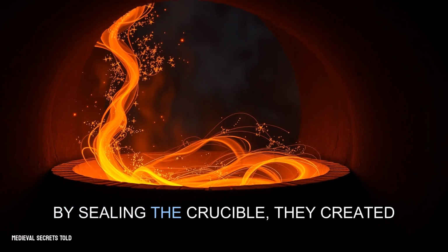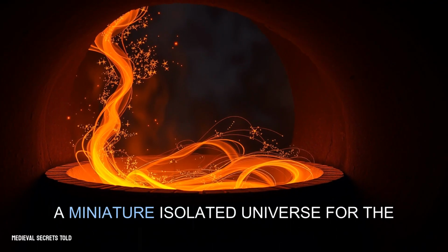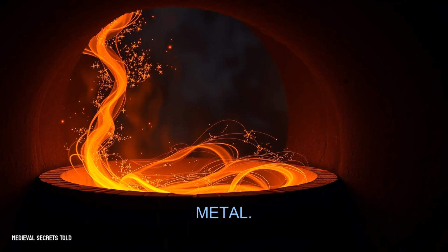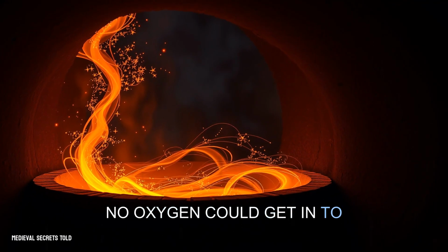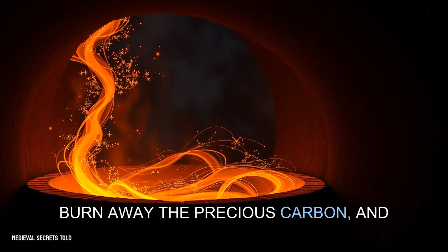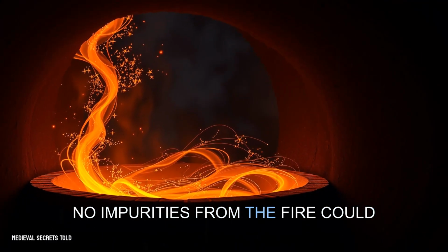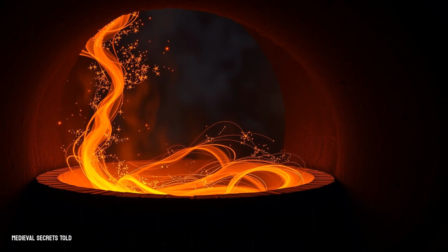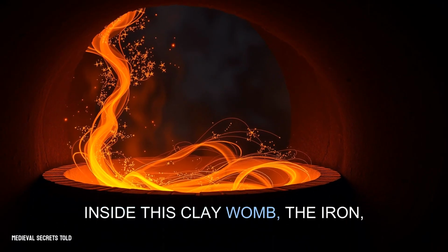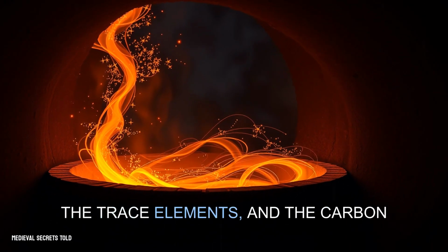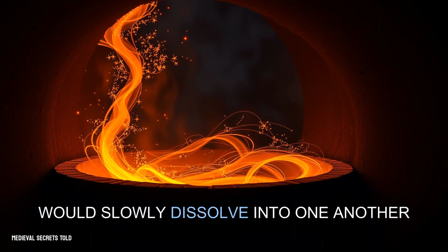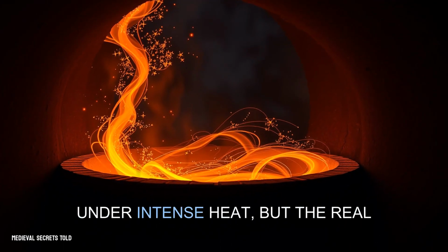By sealing the crucible, they created a miniature, isolated universe for the metal. No oxygen could get in to burn away the precious carbon, and no impurities from the fire could contaminate the melt. Inside this clay womb, the iron, the trace elements, and the carbon would slowly dissolve into one another under intense heat.